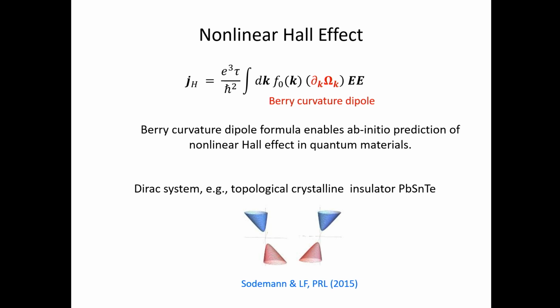And that describes the nonlinear Hall effect. We call this quantity the Berry curvature dipole. It requires both Berry curvature and an asymmetric distribution in k space. Because Berry curvature is routinely calculated now in DFT calculations, this formula allows us to explore the material database and to predict the nonlinear Hall effect.